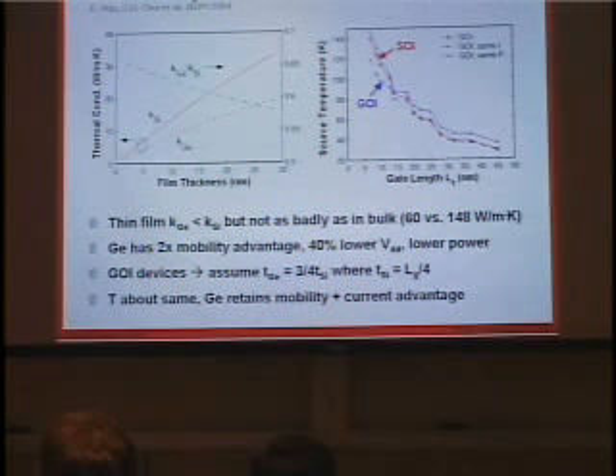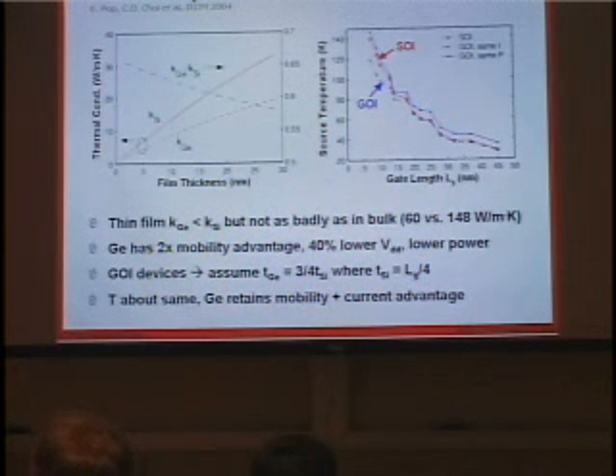Now, when you go to thin films, it turns out they're both bad. They're not quite equally bad. Germanium is still worse, but it's actually a little bit better than when you compare them in bulk. And if you take into account the fact that, in this simulation, I'm making the assumption germanium has a 2x mobility advantage, which is what's available right now in terms of the data out there, and the fact that you can get about the same current drive for 40% lower VDD, again based on experimental data from whatever germanium devices are available right now, you can actually get the same current with lower power in the germanium device. So it's a little bit worse thermally, but you also get less power out of it.